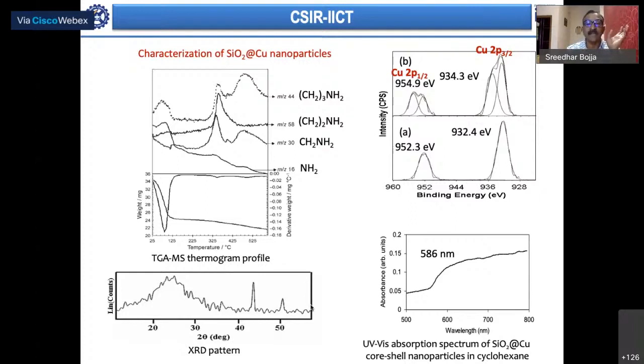Once we've done with that, we did what is called TGA coupled to mass. Thermogravimetric analysis—thermo meaning temperature, gravimetric meaning mass or weight, and analysis. In TGA, the sample is subjected to heat with respect to time or temperature, and you see some weight loss, a decomposition due to the breakdown of the material and its various parts.